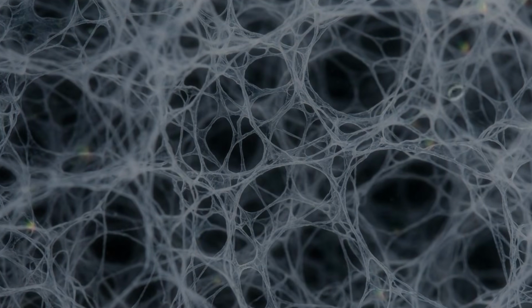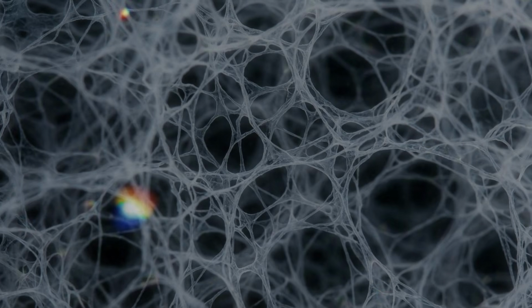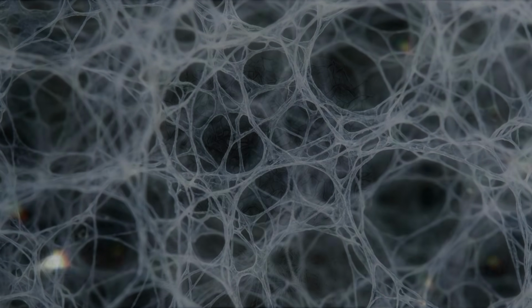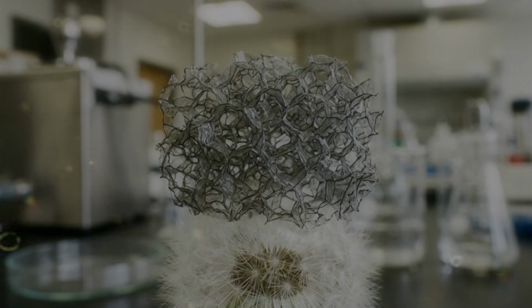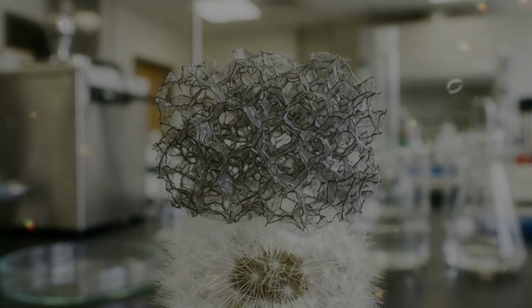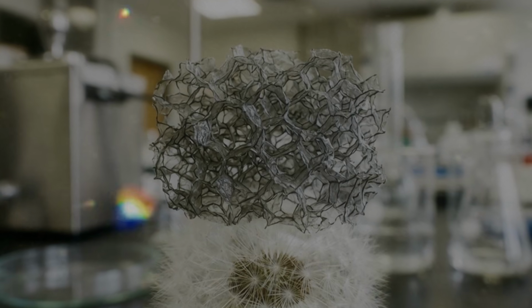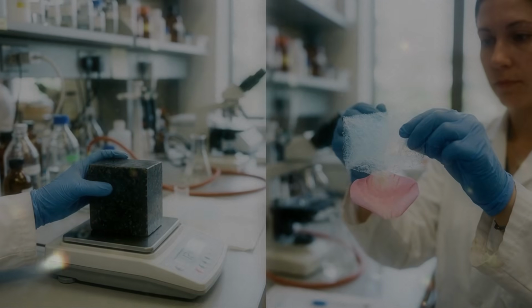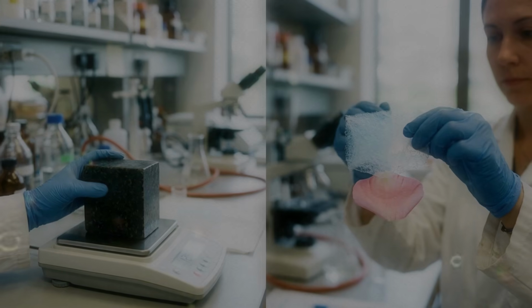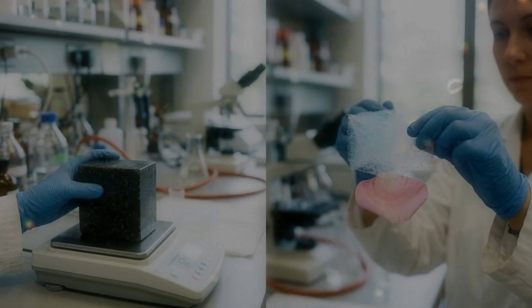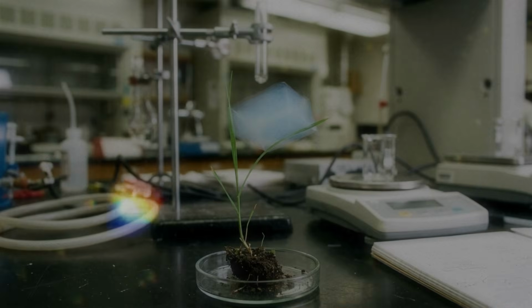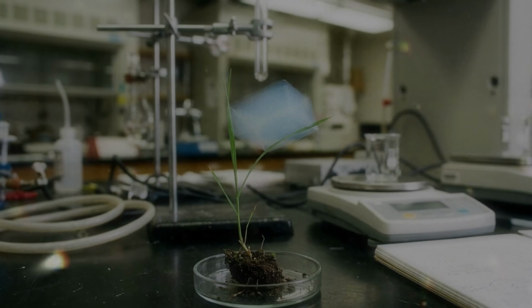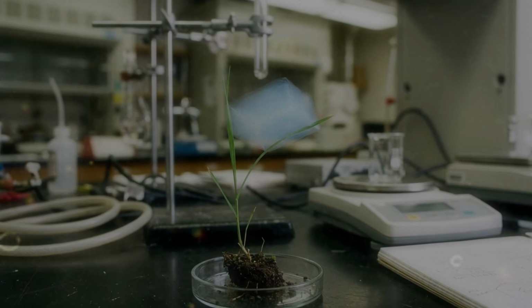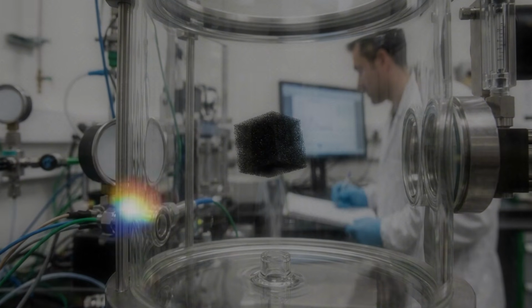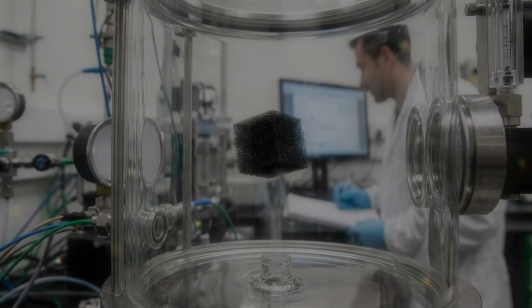Wrinkles help prevent perfect stacking. A crumpled sheet cannot lie completely flat against its neighbor. Small folds create gaps. Nanotubes, particles, or polymer chains can also act as spacers, holding sheets apart. These added materials may strengthen the network or give it new functions. Metal oxide particles can store charge. Magnetic particles can allow the aerogel to respond to a magnetic field. Polymers can improve flexibility. Fibers can stop cracks from spreading.